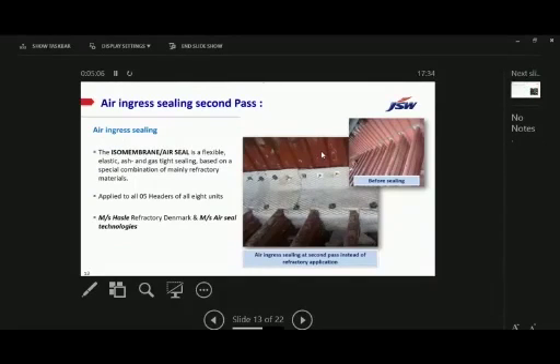Another thing, the sealing of the second pass. In the second pass, there are cold reheater coils that enter the HRA area, heat recovery area, and final superheater tubes and primary superheater tubes, also inlets and outlets in the second pass area. This is with the joint of the HRA wall and tubes. There was an opening that has been closed by seal boxes, which are made of refractory. But due to the continued contraction, shrinkage and expansion of refractory, a gap was created, and that gap allowed hot air ingress that increased the ID fans loading.